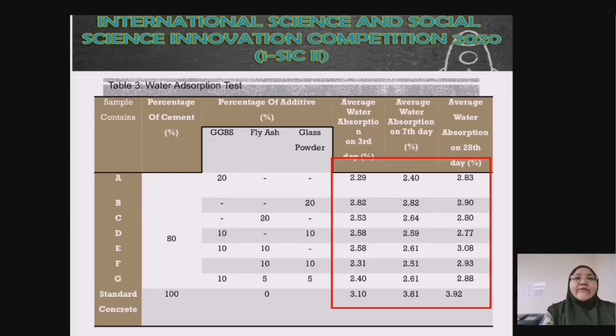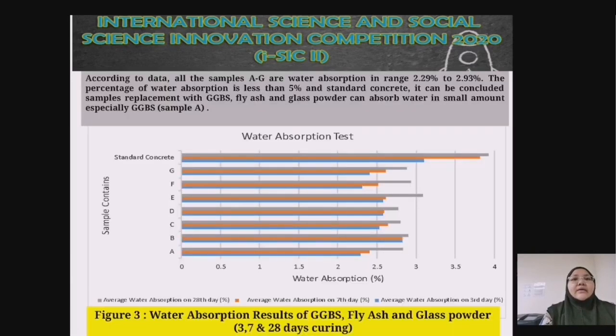This is the result for the water absorption test. According to the data for water absorption test, all the samples A to G have water absorption in range 2.29% to 2.93%. The percentage of water absorption is less than 5% in standard concrete. It can be concluded samples replaced with GGBS, fly ash and glass powder can absorb water in small amount, especially with GGBS sample.